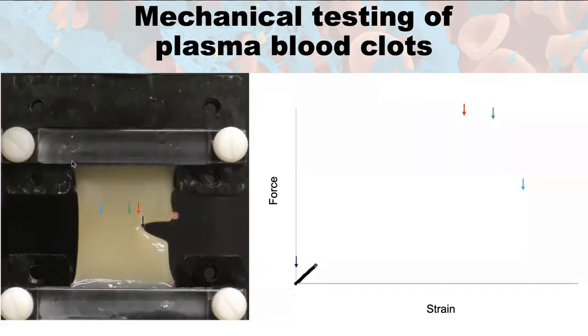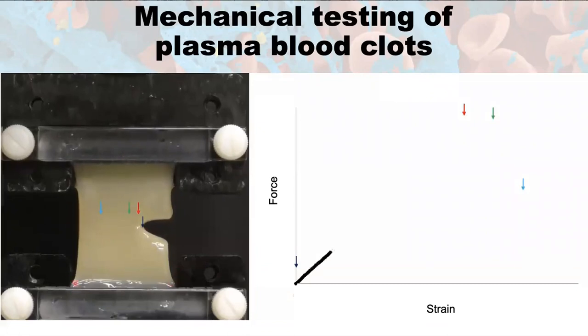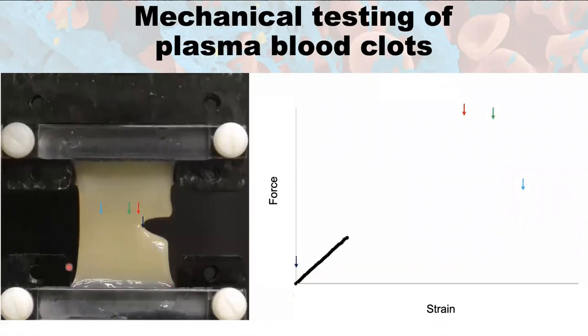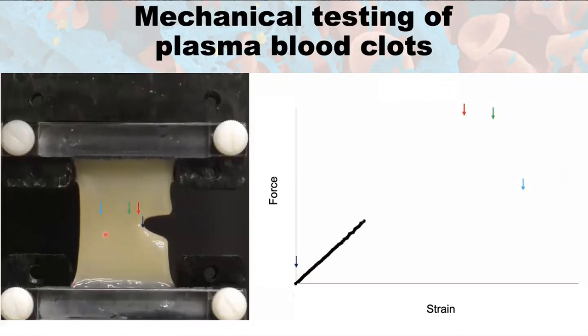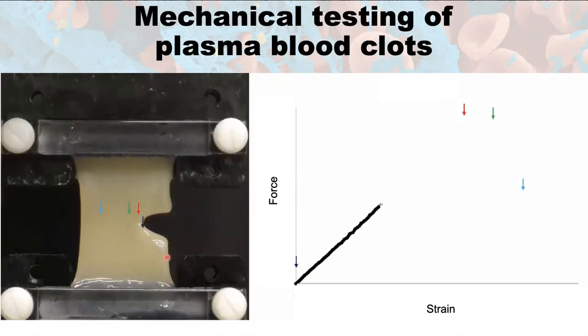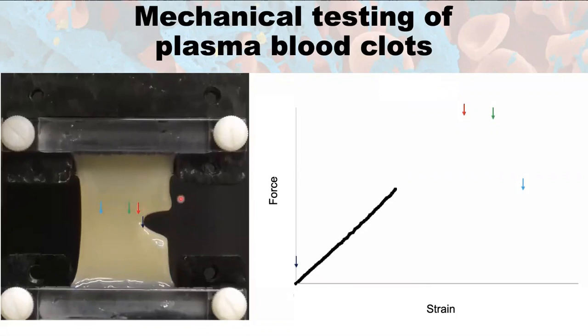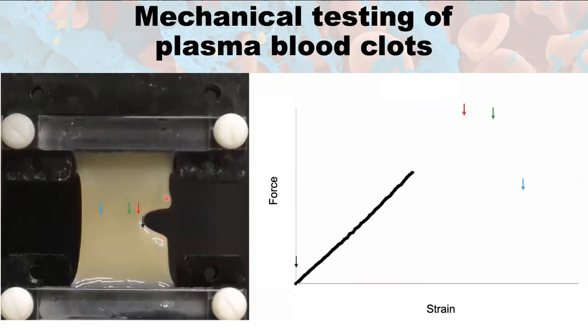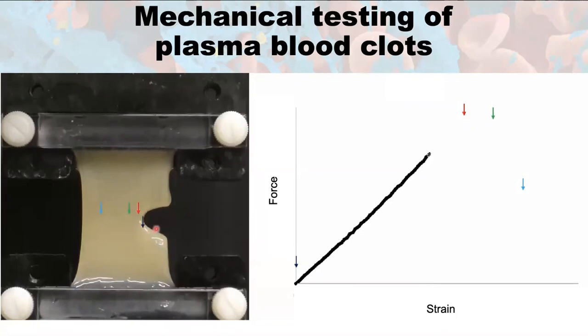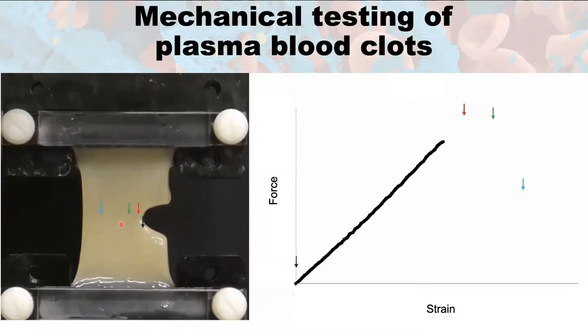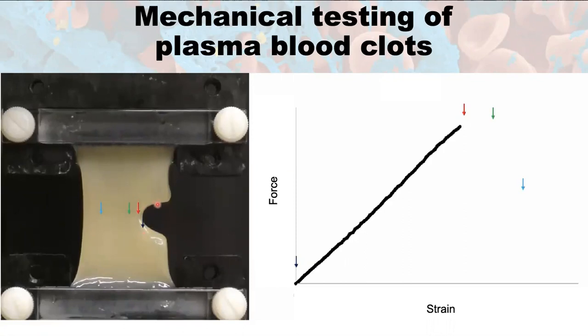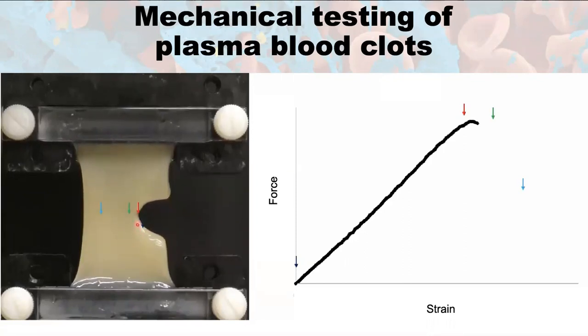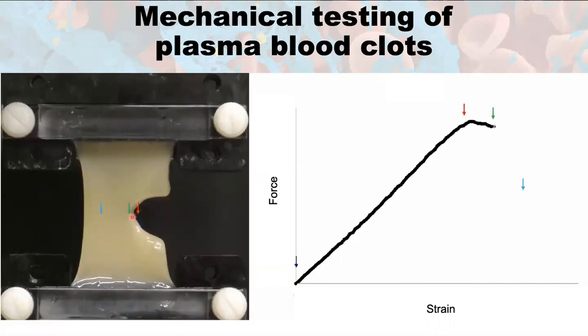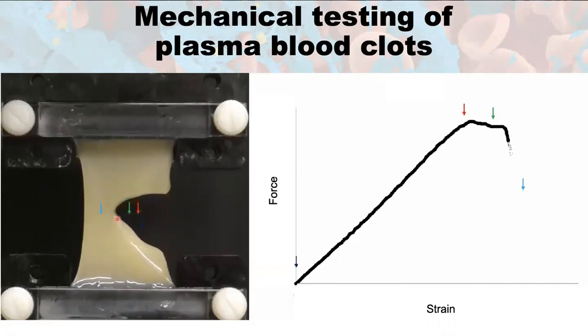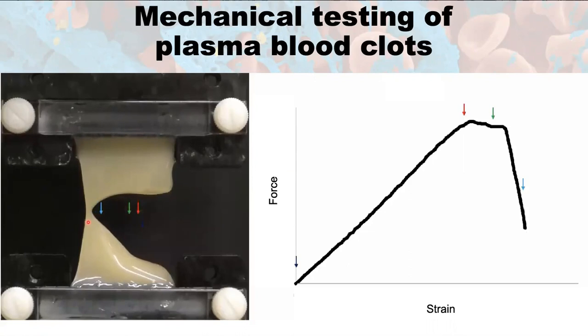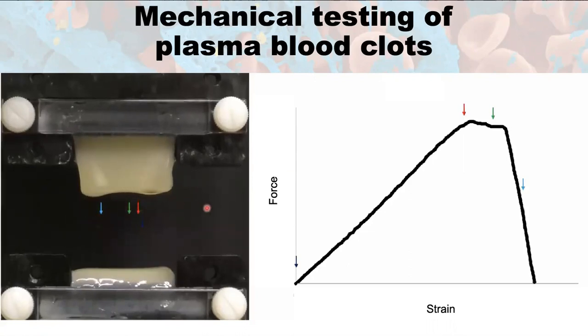So you can see this is a plasma blood clot, and we're loading in the tensile direction, or the vertical direction seen here. You can see that in the beginning, the material on a macroscopic scale isn't changing very much. The crack is widening in the direction of tension, but it's not really growing in that perpendicular direction, up until the point where we reach this critical point. And then the crack starts to travel very rapidly across the sample and ultimately results in the breaking of the